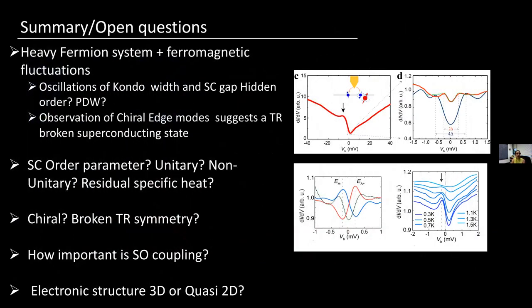In conclusion, it's a very interesting system. It's a heavy fermion compound with a lot of open questions. It sounds as though it might be a non-unitary superconductor — that might explain the residual specific heat, but doesn't explain the thermal conductivity. There's evidence for broken time reversal symmetry and theory suggests it might be chiral. Spin-orbit coupling is presumably important, but we need to really understand its role. We also don't know whether this is a quasi-2D or 3D electronic structure — it might be both. There's a lot of missing information on this material.